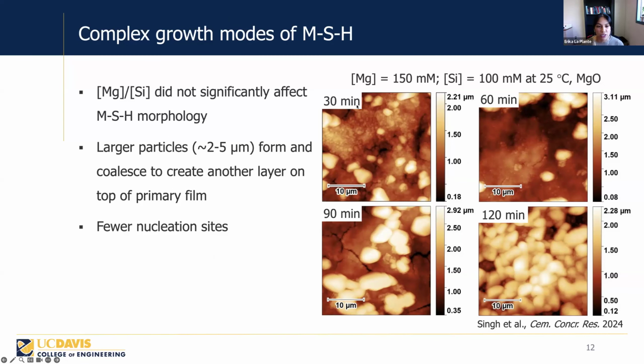But then at greater reaction times, you also observe the formation of larger particles that form and then coalesce to create another layer on top of that primary film. So these are larger particles that are 2 to 5 microns in size. And this suggests that as we increase the reaction time, the solution's supersaturation decreases. And this could be what is causing the creation of fewer nucleation sites. So we have larger grains at longer reaction times.